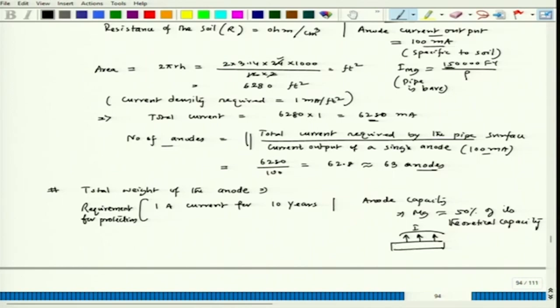Like, for example, there could be local cells. So this is positive, this is negative, that local cell forms. So the current will flow from the anode to the cathode through the soil, so this part will dissolve. So that time we have self dissolution, but in a theoretical situation all the cathodic reaction must happen on the pipeline, but that cannot be possible in an actual situation. So that's where the efficiency drops down. So magnesium operates at 50% of its efficiency.